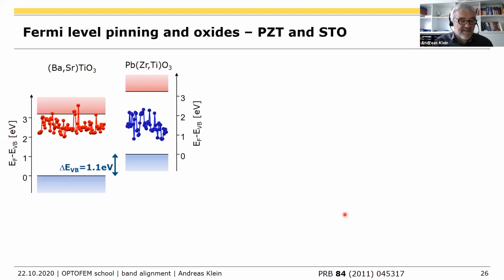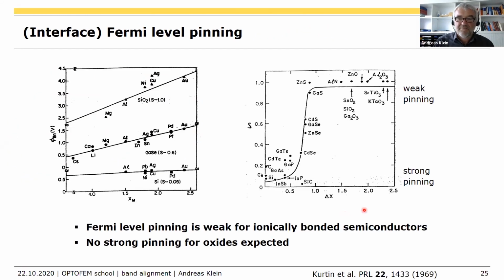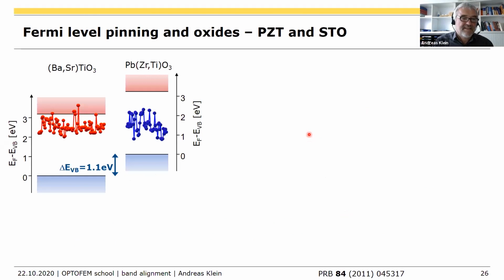Now, what about the oxides? I guess for this school, many people are interested in the oxides. So what about the Fermi level pinning for the oxides? Well, here people say already there should not be much pinning, but we can also get that explicitly. So here is the band alignment between barium strontium titanate and lead zirconate titanate. The energy bands here are a little bit higher. Each data point here is a Fermi level position measured at a thin film surface of this material, or here for PZT as well. But that's not the important point.